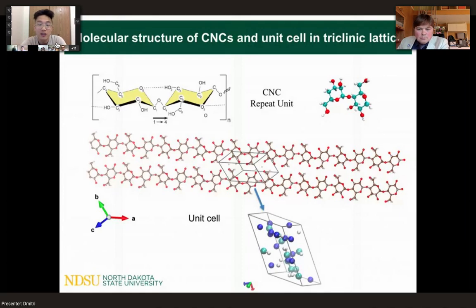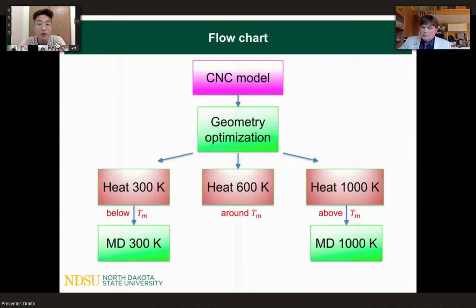Here is a schematic figure showing what the molecular structure of cellulose nanocrystal looks like. The unit cell in a triclinic lattice has been used for the computational model. Geometry optimization is done first to make sure of the local energy minimum state, and then heat is applied from 300 K to 1000 K. For cellulose nanocrystal, the melting temperature is around 600. So we choose three typical temperatures: well below the melting temperature, approaching it, and even well above it.